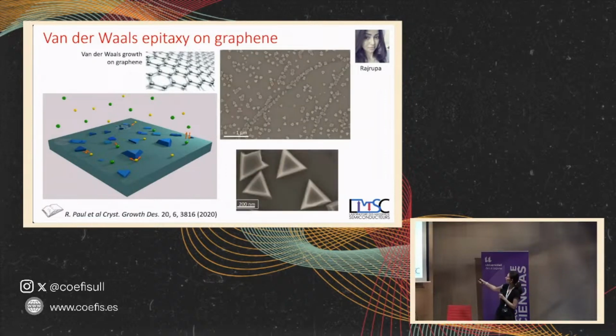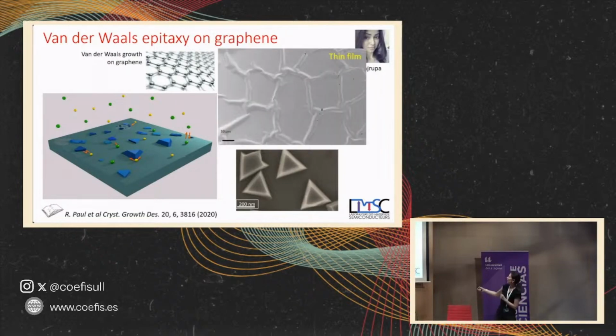And this is how it looks. You see the crystals decorating the defects of the graphene, the crystal boundaries, and then you grow them. And some of them are oriented in the same direction. When they merge, they create a thin film. And this is an example of a thin film. So there is some bubbliness because of the graphene, but you see that you can create a thin film there that has very high quality.